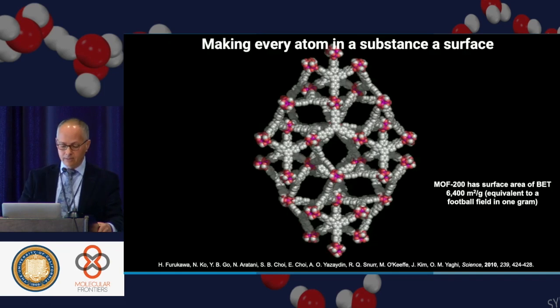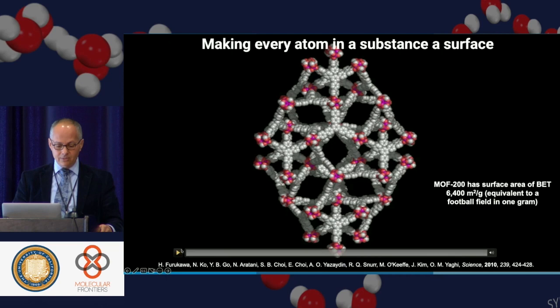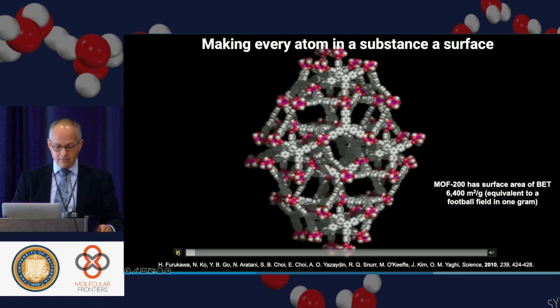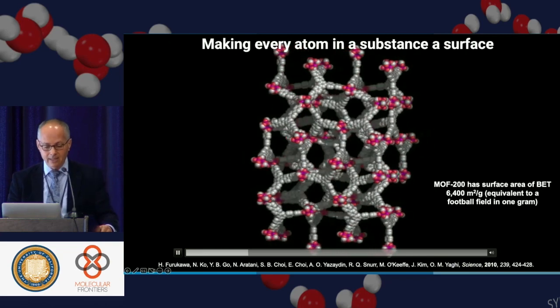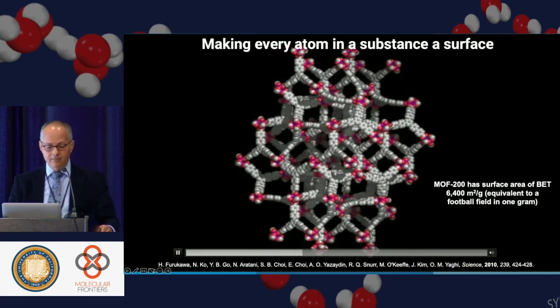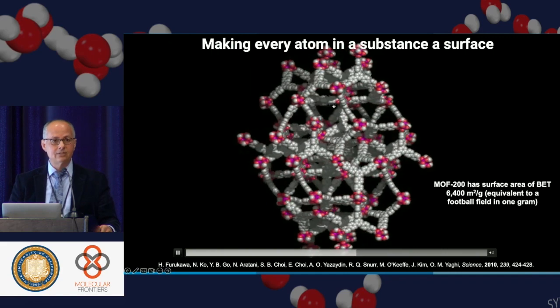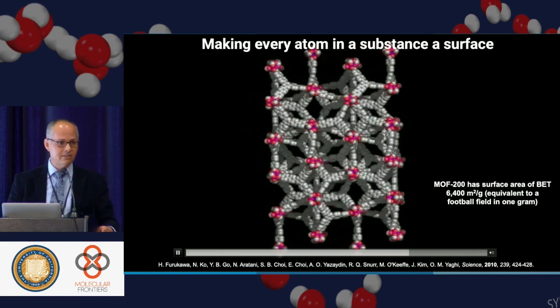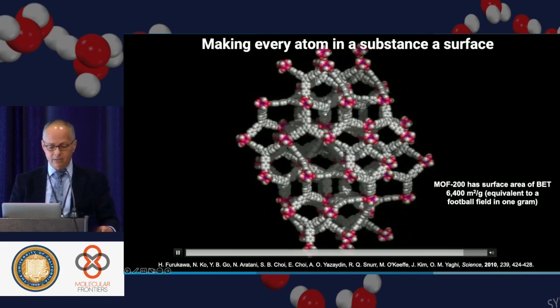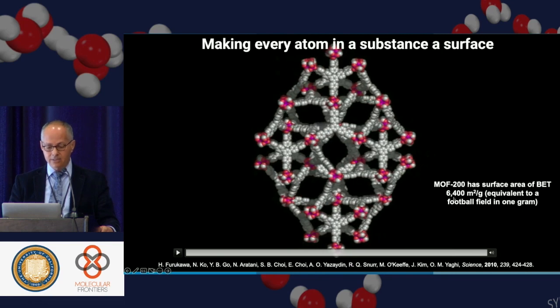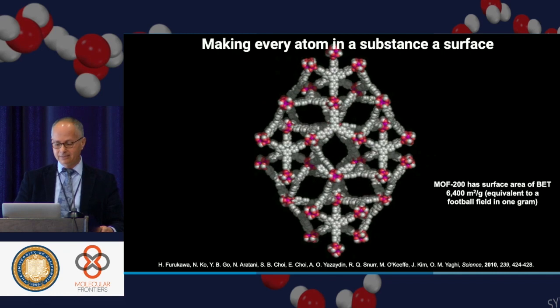So once we have identified the adsorptive sites, now my students very quickly can go to the lab and link longer linkers that have more and more exposed edges and faces, and with that metal oxide unit. And now you have a material that has a surface area of 6,400 meters square per gram, okay? It's unimaginable that you could make a material that has such a high surface area.